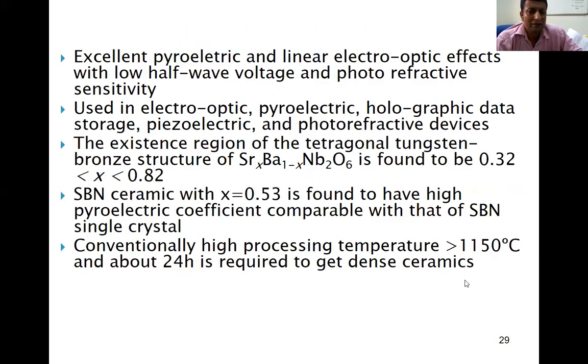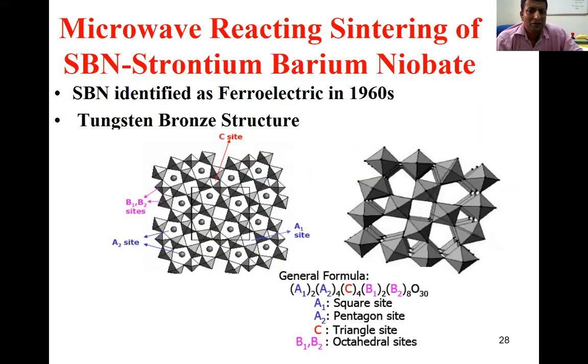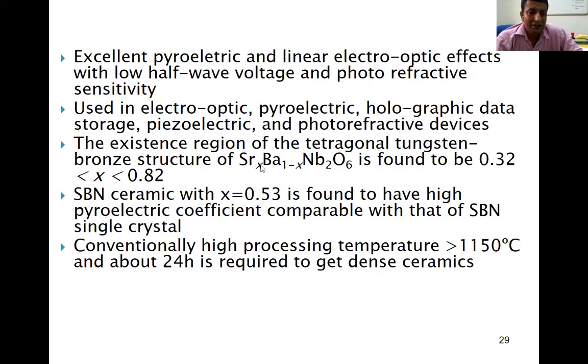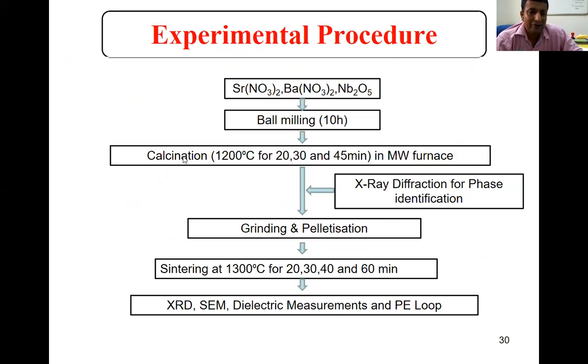Just a minute, I'm going back. What we did here was reactive sintering. What is this reactive sintering? In the calcination time durations we chose 20, 30, 45, and the whole purpose of calcination is that we should get the single phase. That is the whole purpose of the calcination process.